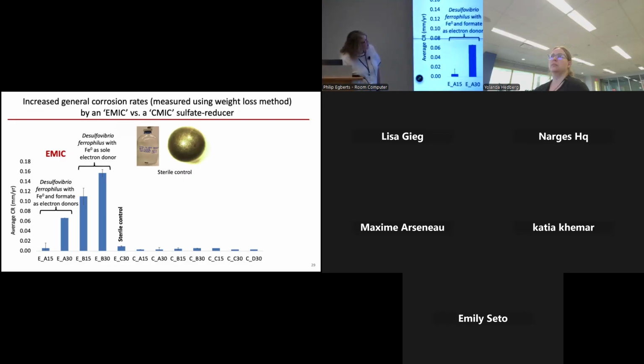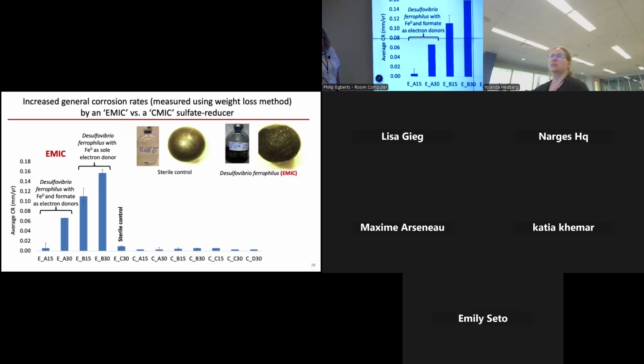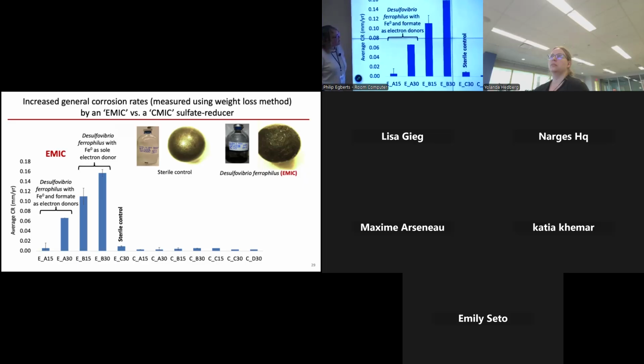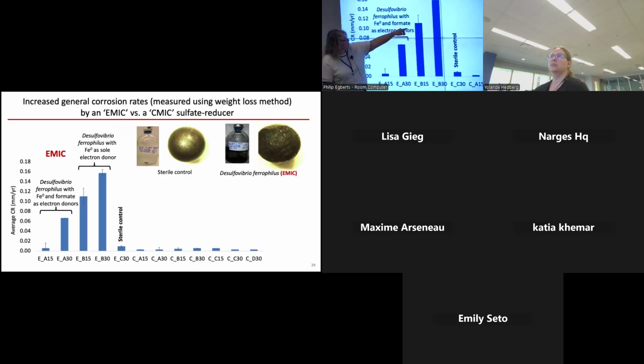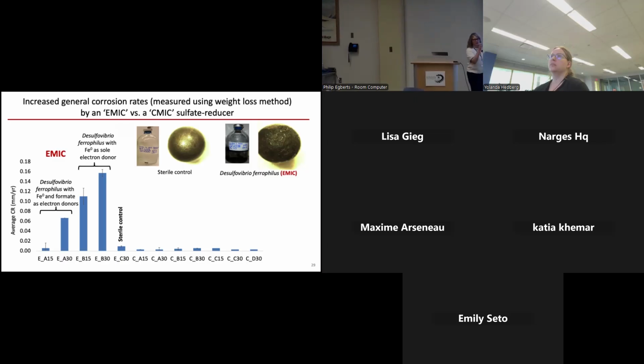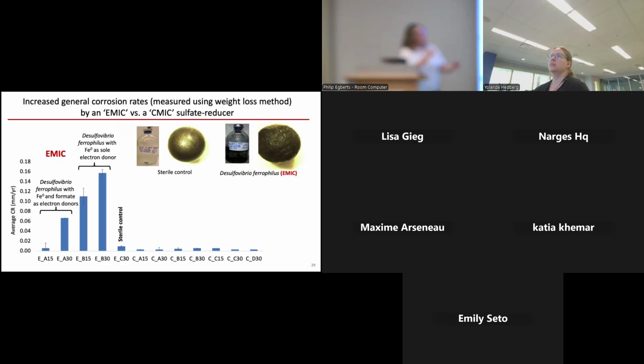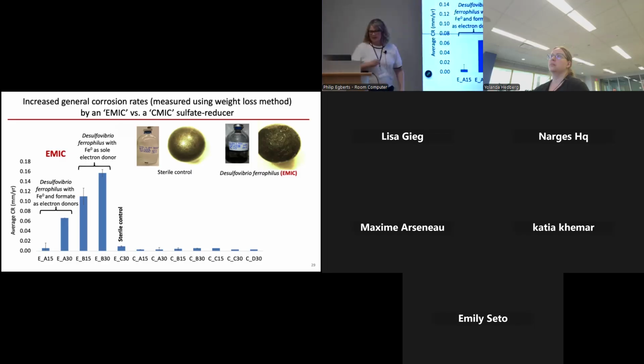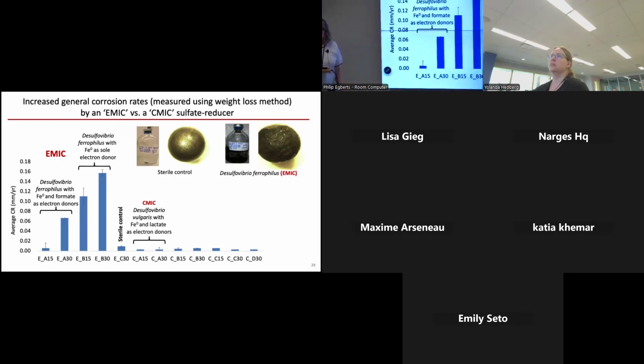We did this with little beads, which we're going to tell you about a little bit later. They look shiny and clear. But when we took beads out of the bottles with the EMIC organism, you can see that there's a lot more pitting and damage happening on that metal. Again, this suggests that those microbes are eating up that metal, using it as an electron donor.